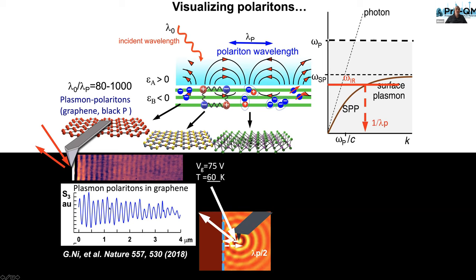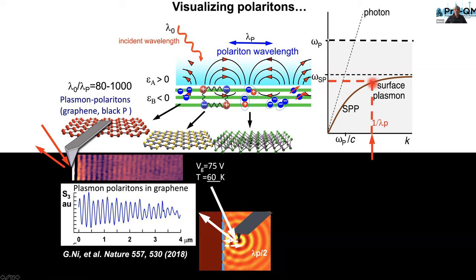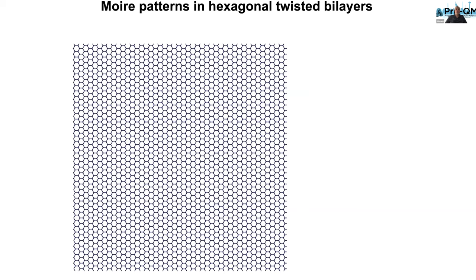You see that plasmon polaritons are still compact, but can travel over microns inside the crystal because the losses at low temperatures are fairly low. From these oscillations, we read the relevant k value. We know at what frequency we do the measurements, and at the intersection of these two points we get an experimental result for this dispersion. We have to do it point by point if we work with monochromatic lasers. So this is a tedious process, but doable. Or in some situations, we can use broadband lasers and then determine a large segment of this dispersion in one shot.